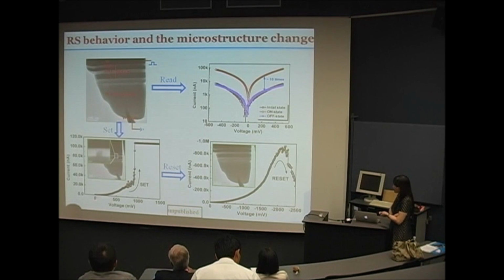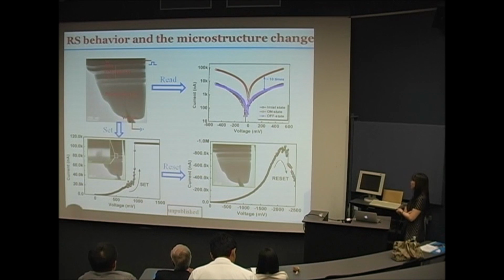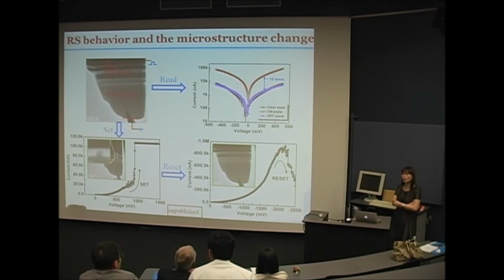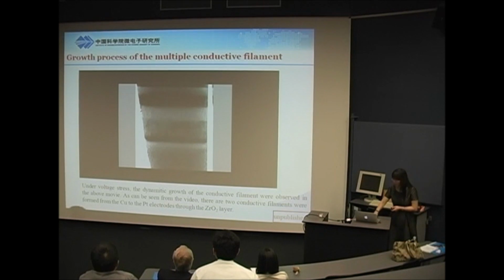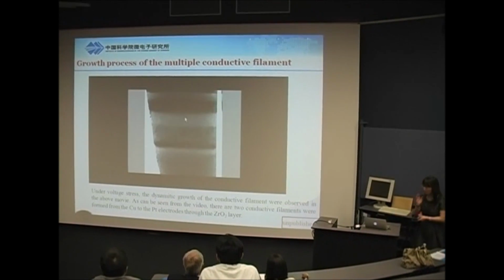We can see that when the set process is triggered, the current increases largely, and at the same time, from TEM we can see this filament was formed. This is the enlarged picture. For the reset process, you can see the current decreases largely, and the filament also disappeared. I think this is the first time we observed this dynamic process. Here I just show a video, but maybe it is not so clear. It needs maybe a minute or so. So it's just the beginning.